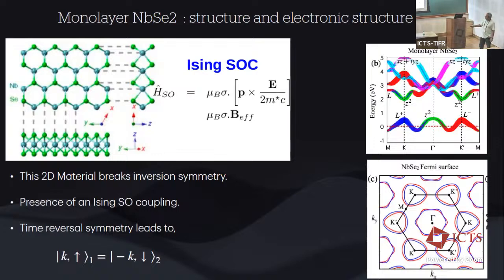So for every point k with spin up, there is an equivalent point, minus k with spin down, but because of the spin orbit splitting, these two correspond to two different bands in your system. So if you look at the electronic structure generated from DFT, there is primarily, at least ignoring spin orbit coupling, a single band which forms the Fermi surface of the system, which creates a pocket centered at the gamma point and pockets at K and K prime points.